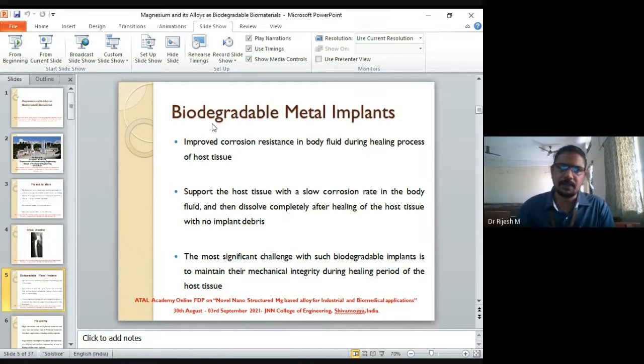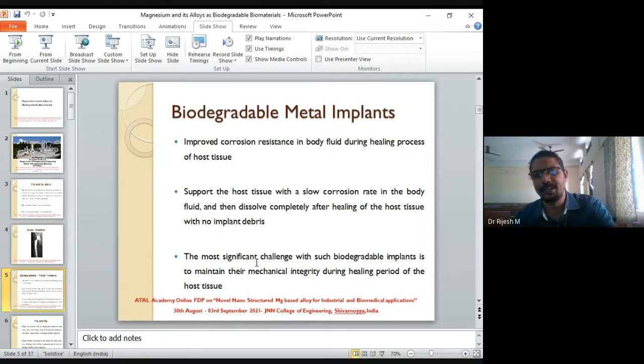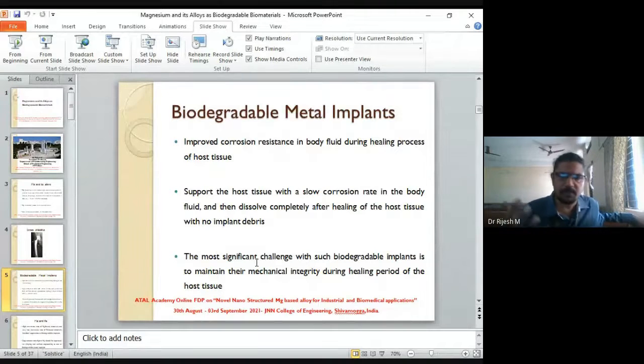The ions that have been released from magnesium are being used by the body. I mean to say that the corrosion that has been taking place, strictly speaking, should not happen. So even if it happens, the body will take it up thinking that it is the magnesium that I'm getting for metabolism. So in that case, magnesium works as a wonderful biodegradable metal implant. The most significant challenge with such biodegradable implants is to maintain their mechanical integrity during the healing time of the host tissues. Now, when it is getting corroded in this fashion, will the mechanical strength of this implant be the same, or will there be a decrease in mechanical integrity? That is a big question, and that's the challenge in these biodegradable metal implants too.